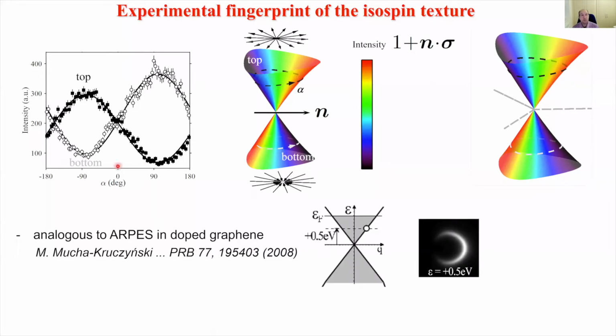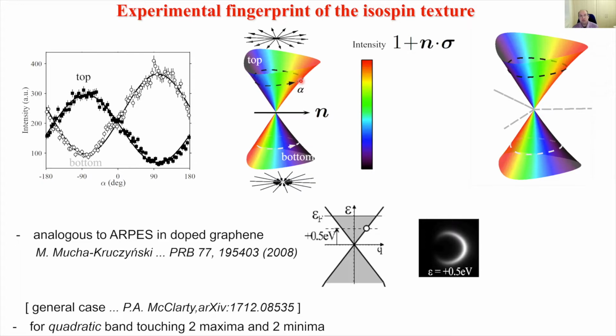And this type of intensity modulation is completely analogous to what's been seen by ARPES measurements in doped graphene. So here is a constant energy ARPES measurement at an energy just below the Fermi level. This is for doped graphene. And you see the intensity is non-uniform, but has a bright spot, dark spot, and comes back to bright. This is completely analogous to the intensity modulation here, strong, weak, strong. Because fundamentally, the form of the wave function and the same isospin concept also applies in this case. So this type of intensity modulation is a characteristic signature of the topological property of the nodal point.